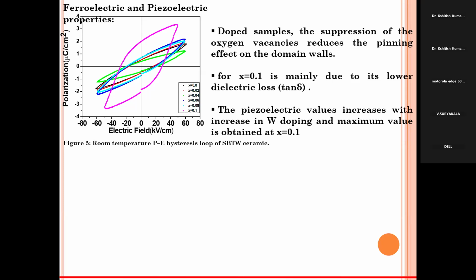Then we have to find out the ferroelectric property, and here this is the ferroelectric P-E loop, and the pink one is the P-E loop for x=0.1, and we got the saturation polarization and remnant polarization also increases in that material, with the doping material. It is highest for x=0.1, and if we compare the dielectric loss, that material has the lowest dielectric loss. So now we have two advantages: the relaxor property is good, and the second is a better ferroelectric material, means polarization is more in the doped material, and it will be better for the x=0.1 compound.